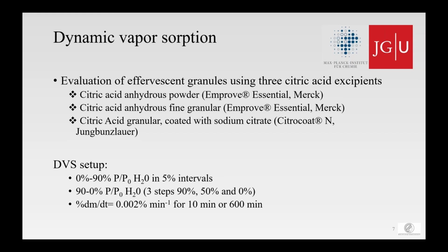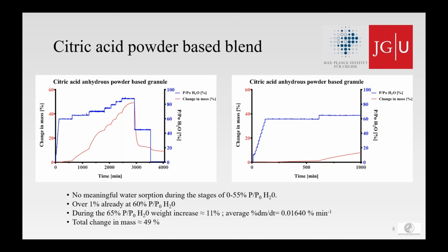So now we're going to take a look at the powder-based blend first. What you can see here is the experiment that I just described, and what we saw was that we have no meaningful water sorption measured during the first stages of 0 to 55% relative humidity. And at 60% relative humidity already, the sample increased 1% in weight already. Then during the 65% relative humidity stage, a high amount of water sorption took place. The sample increased its total weight by roughly 11%, at an average mass increase per minute of 0.016%. The total mass change was roughly 49%, which is quite a lot for water sorption.